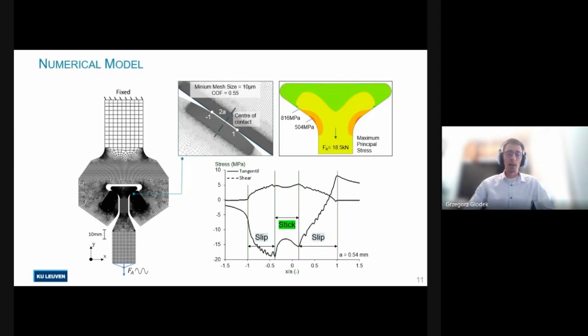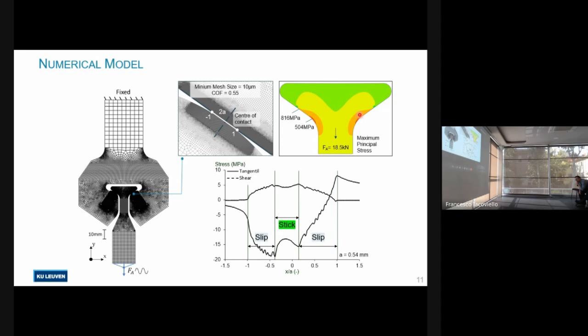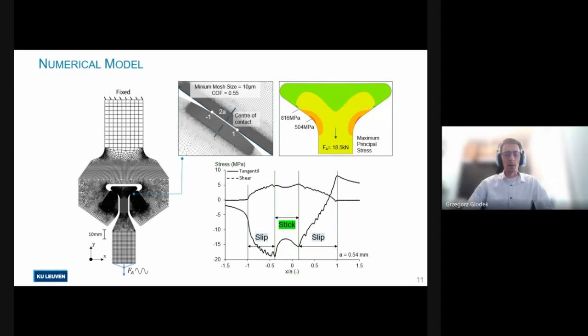A convergence study revealed that the minimum mesh size should be 10 micrometers, and the used coefficient of friction was equal to 0.55. Now, if we look at the principal stress contour in the dovetail portion of the sample, we can see that there is a stress concentration at the edge of contact, but there are also high principal stress fields at the curved edges as well, which is important to keep in mind.